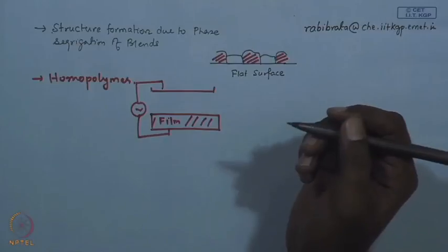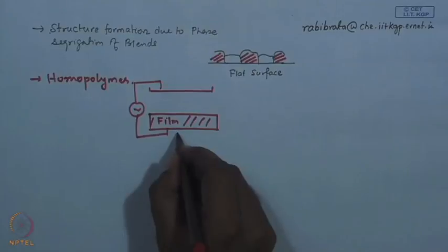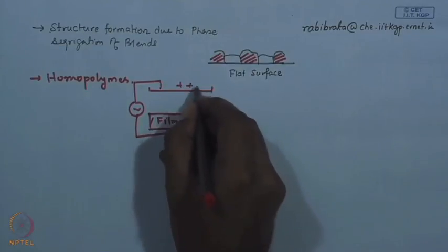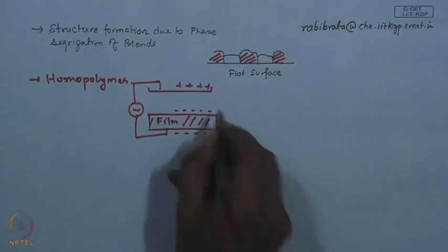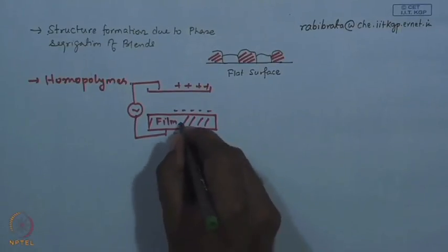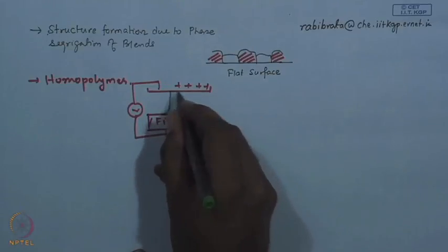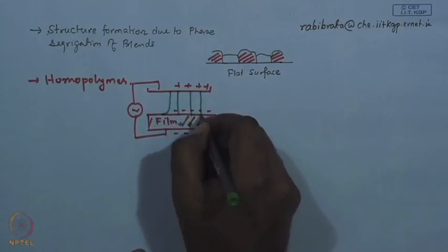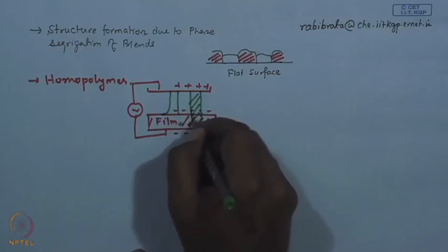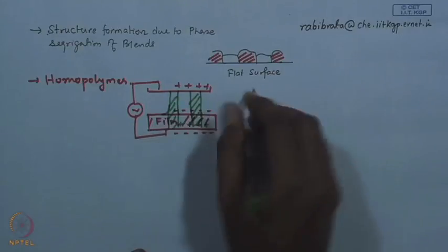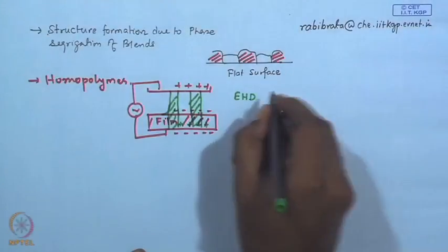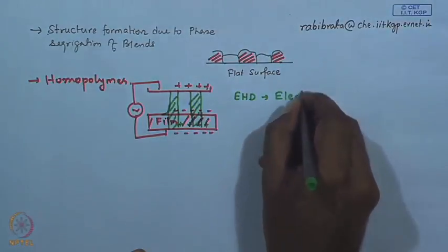destabilizing field arises because of interfacial van der Waals interaction. Here you apply an additional field, which can be an electric field, a thermal gradient, a magnetic field or whatever, and the application of this field eventually results in polarization of this dielectric film, which is a polymer film in a capacitor geometry. Therefore, if it is in a liquid state, it aligns in the direction of the field, forming columns. This is what is known as EHD instability, or electrohydrodynamic instability.